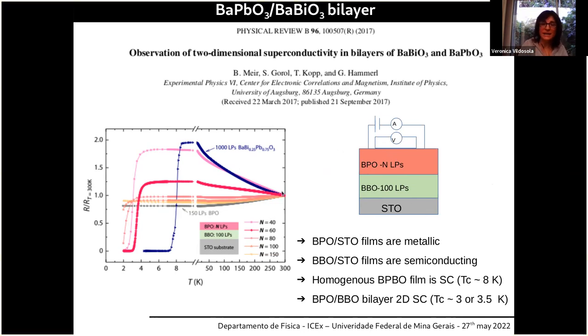So they observe that the system, this is the resistance with temperature. Here is a very large mix of barium bismuth lead oxygen, like a bulk sample, that has the resistance that goes up when the temperature goes down, and then suddenly below 7-8 kelvins, it becomes superconducting. This is what they call the bulk situation, because they are completely mixed. But when they build this bilayer separately, they observe that for a given width of the BPO, the system also becomes superconducting, below 3.5 kelvin, or for some thinner films, below even 1 kelvin.